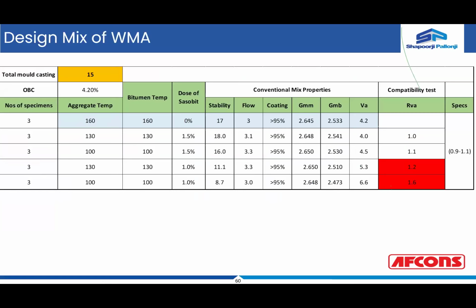Now if you see a trial which is being shared, this is particularly the doses of the Sasobit material, which is in the range of 1.5%, 1%. And if you see the aggregate temperature, the first line is talking about the number of specimens being casted at optimum binder content of 4.2%, and your aggregate temperature is varying from 160, 130, 100, 130, and 100, and then your bitumen temperature is also 160, 130, 100, 130, and 100.